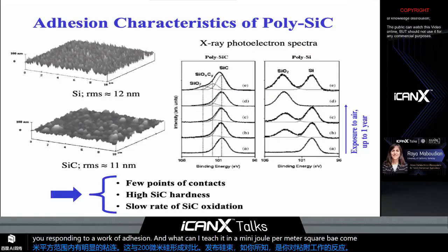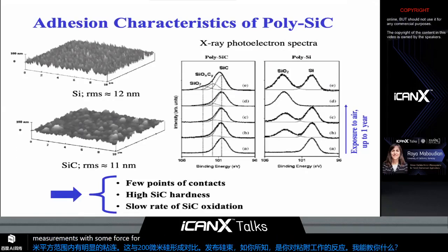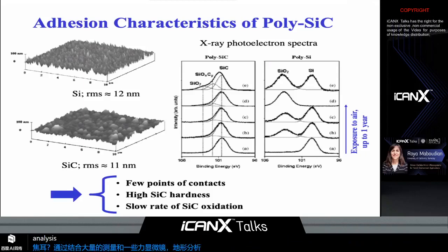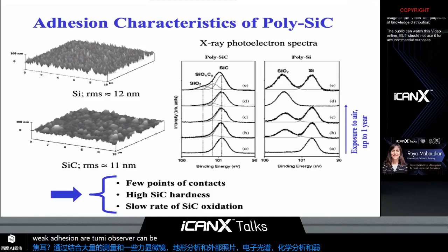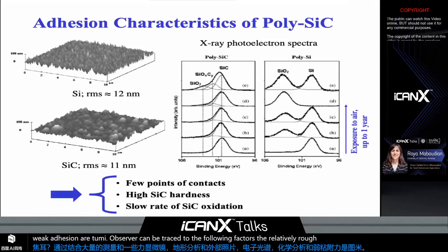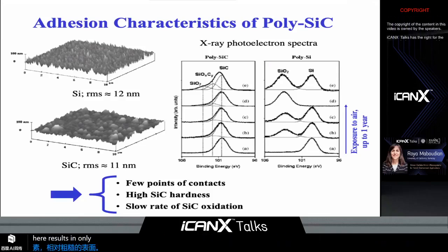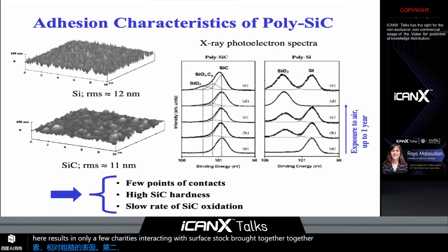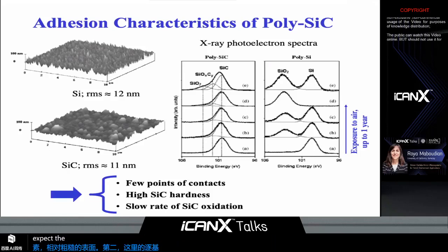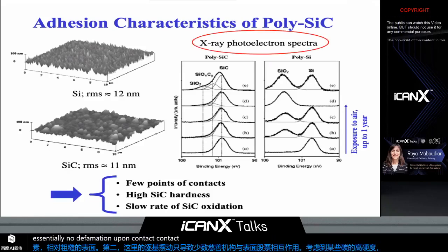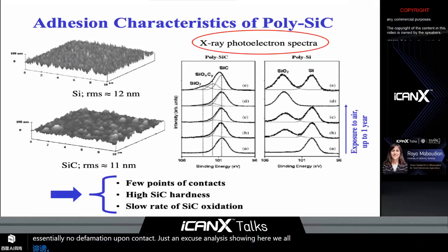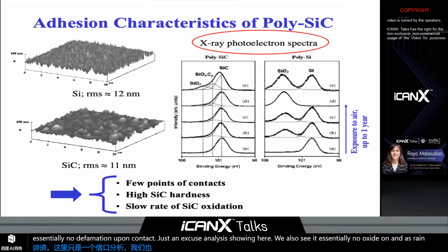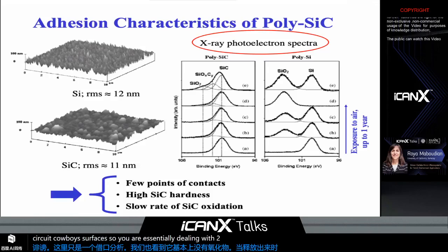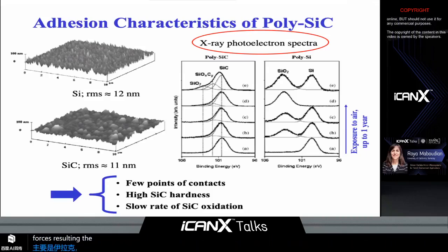By combining the adhesion measurements with atomic force microscopy topographic analysis and X-ray photoelectron spectroscopy chemical analysis, the weak adhesion that we observe can be traced to the following factors. The relatively rough surfaces of silicon carbide substrate, shown here, result in only a few asperities interacting when surfaces are brought together. Given the high hardness of silicon carbide, we expect essentially no deformation upon contact. Based on XPS analysis shown here, we also see essentially no oxide growing on as-released silicon carbide surfaces. So we are essentially dealing with two rough surfaces that primarily interact with van der Waals forces, resulting in the low adhesion values that we observed.